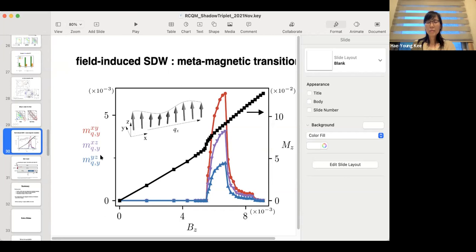Yes, that is the spontaneous one. So the spontaneous SDW will have a y component, while the ordering wave vector will be in the x direction. These three are the magnitudes of the spin density wave in different orbitals. In the experiment, you are going to see all of it together. I don't think there is a way to differentiate them. They're all mixed when you are doing a measurement. I see, they're all along y. Okay, I see the y at the bottom now. Yeah, okay, very good.